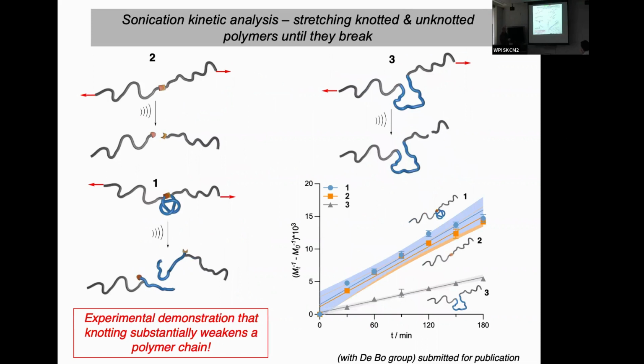So if we look at compound 3, this is just where we've got the ligand that isn't knotted in the polymer, and this is just showing how easily broken the polymer is. This is a polymer that isn't easily broken because it has a very shallow gradient here. If we look at this polymer 2, this is the one that has the very easily broken group, the mechanophore in it, but it doesn't have a knot. And that is a much more easily broken polymer than this one.